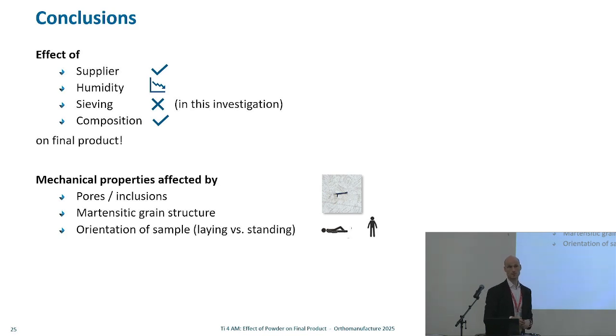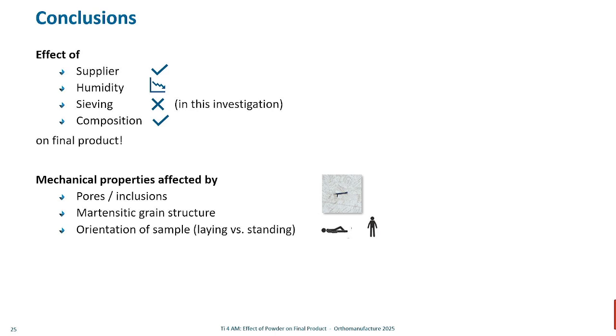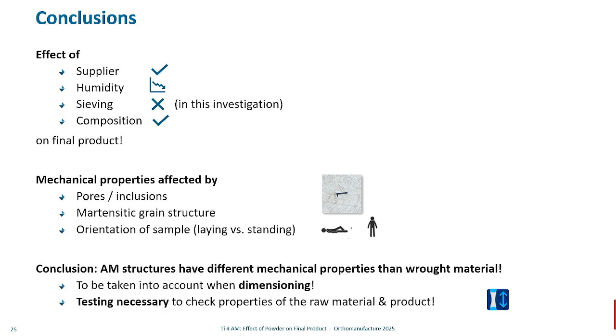We had seen that there were some pores all over the samples. So that's a material property which we have to face when dealing with 3D printed materials. Often we had martensitic grain structure, which is different from the alpha-beta grain structure we usually face using these materials. And we have seen that the orientation really plays a role, so the properties are not really homogeneous in both directions. So material properties do differ from the bulk material of forged alloys, so this has to be taken into account when designing and producing something.